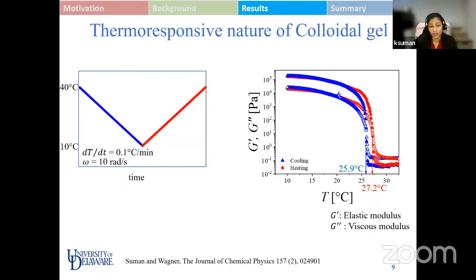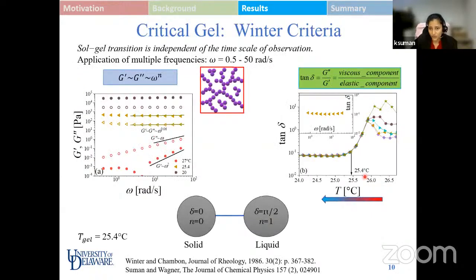However, one drawback of this nomenclature is that in this case, the temperature of the gel point is dependent on the applied frequency. So in order to have an accurate characterization of the gel point temperature, we apply multiple frequencies to the system, which is known as the cyclic frequency sweep experiment. This idea was proposed by Winter and is widely known as the Winter criteria. At the point of critical gel transition, when the system forms the weakest space-spanning percolated network, both the elastic and the viscous moduli are known to show identical power law dependence on frequency, given by the equation over here. So the exponent n is identical for both G prime and G double prime.